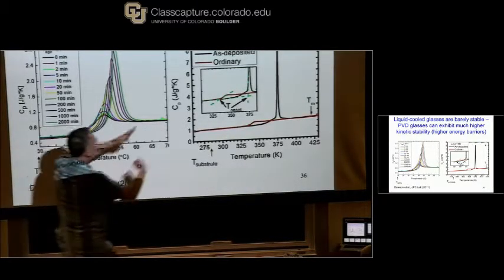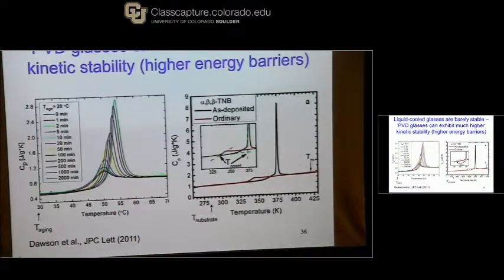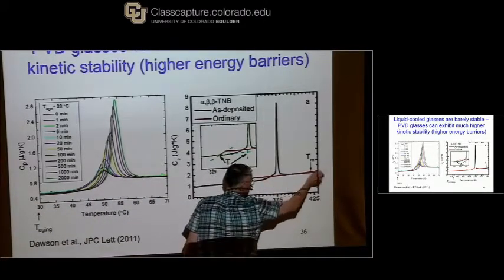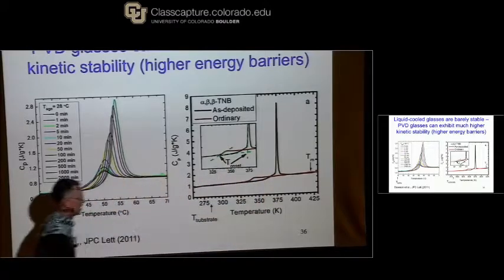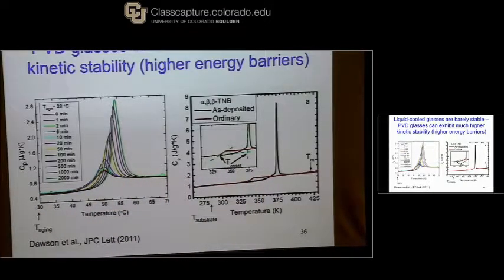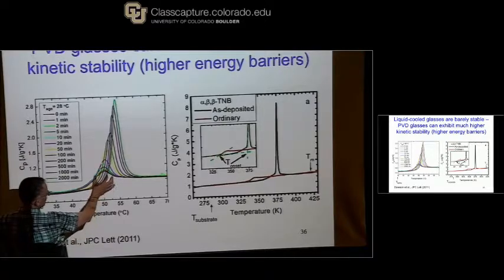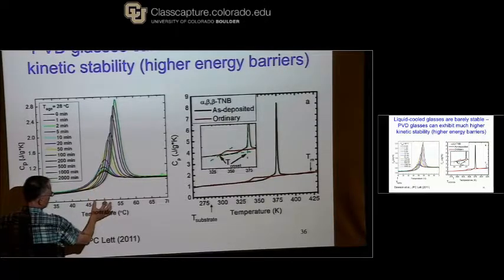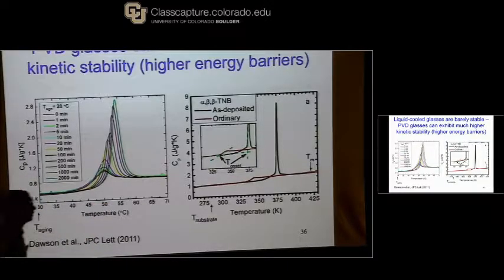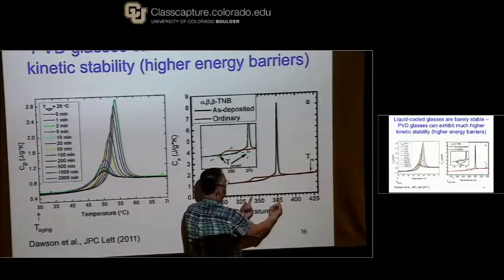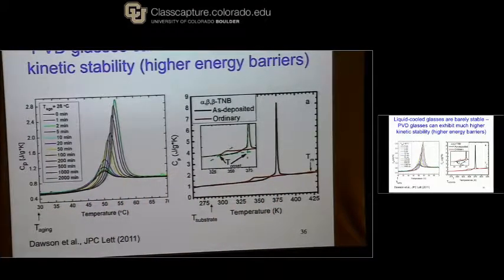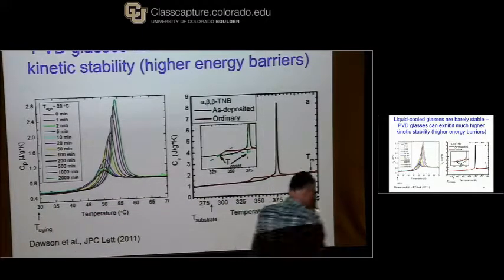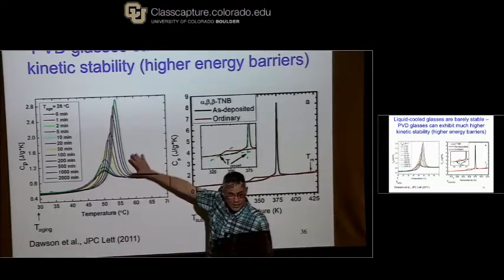On the right-hand side, I show you curves for a different molecule, but that illustrate the same experiment. This is the behavior of the liquid-cooled glass. This is the behavior of the vapor-deposited glass. These are different molecules, but this is still a fair comparison. Here we increased our aging time by about 2 orders of magnitude. We moved up our onset temperature by 3 or 4 degrees. Here we moved up our onset temperature by about 35 degrees. If you want to try and make a comparison, these are experiments where you age for up to 1 day.